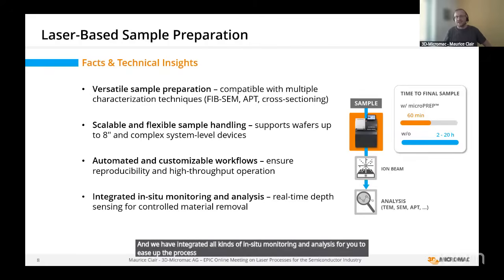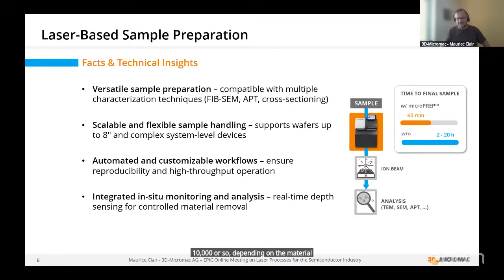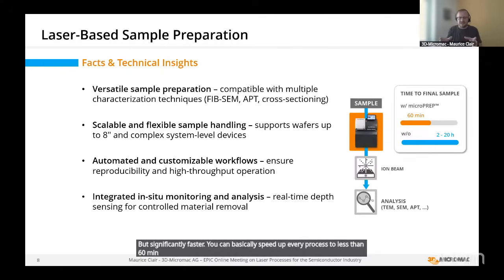And the basic idea, shown on the right-hand side, is that if you prepare a sample with the ion beam, it can take you 2 to 20 hours. But because the ablation rate of our laser is higher by a factor of, I think, 10,000 or so, depending on the material, you can speed up every process to less than 60 minutes. And the majority of the time is then still putting in the sample, preparing the recipe, starting the process, and so on.